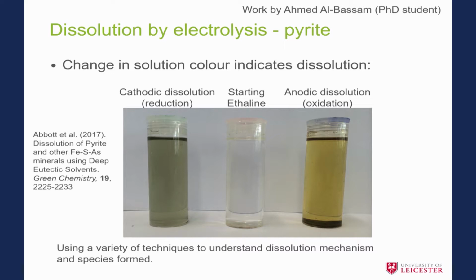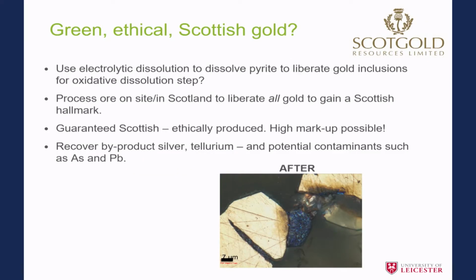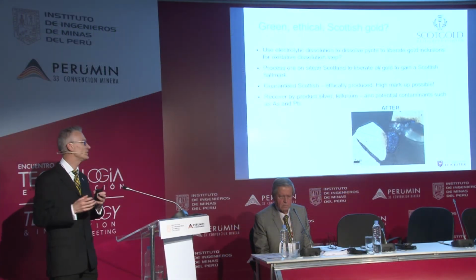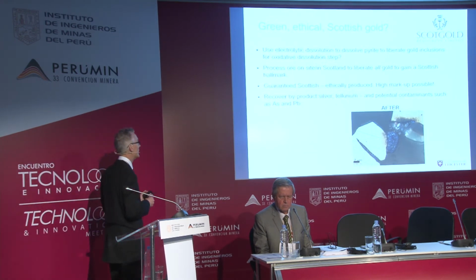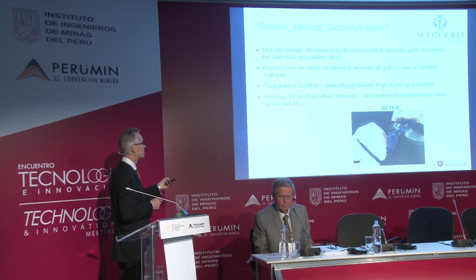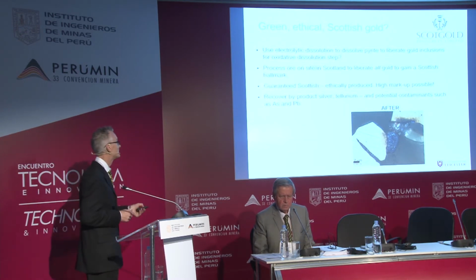And pyrite, interestingly, can dissolve both by oxidation and reduction, giving us great flexibility in the way that we actually deal with it. So for our little mine in Scotland, this could make a really big difference. We could use electrolytic dissolution to dissolve the pyrite, liberate the gold, and gain a Scottish hallmark for all of that gold. It can be guaranteed Scottish, ethically produced, and gain a high markup. But alongside that, we can recover byproducts, silver, tellurium, etc.